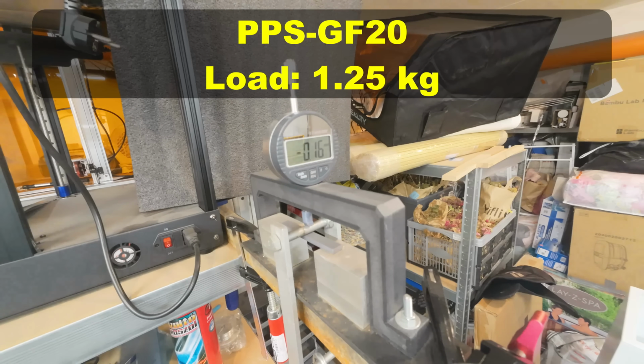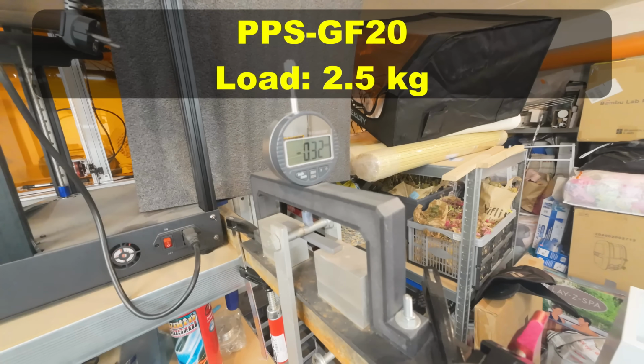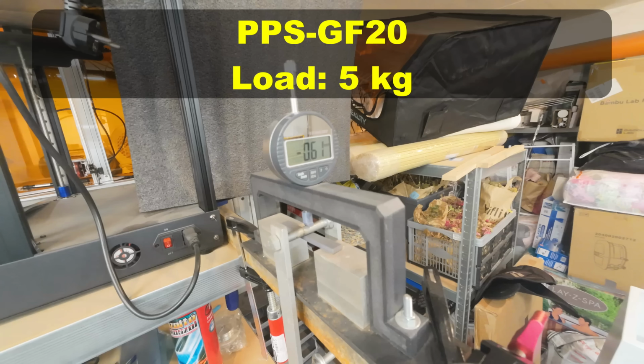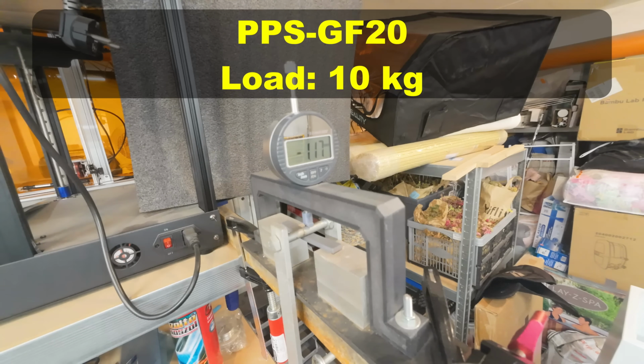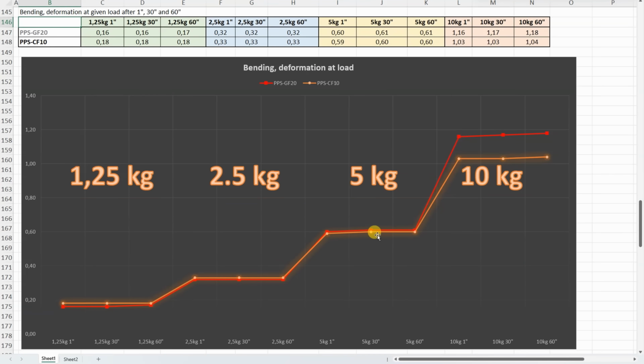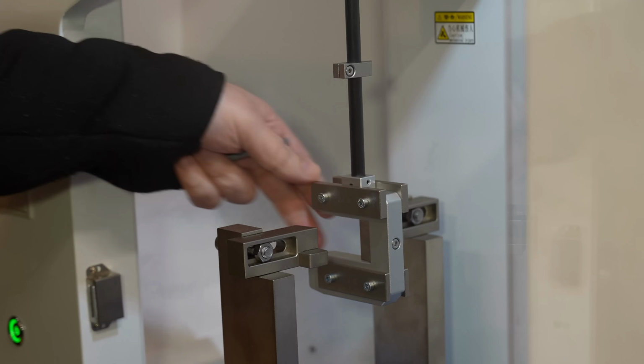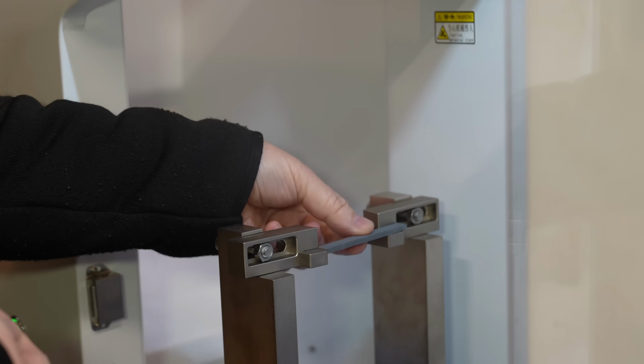Three-point bending test, distance between supports is 50 mm, and I'm measuring the deformation under these loads after 1, 30 and 60 seconds. Currently this is deformation under 5 kg and under 10 kg. On smaller loads, the deformation is very similar between these two materials. Now at 10 kg, a little bit more deformation on the glass fiber version, but in both cases, this is a very stiff material.